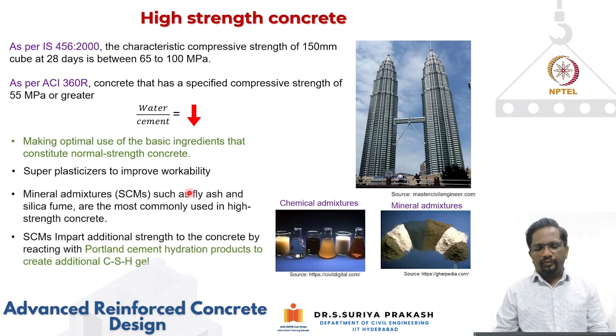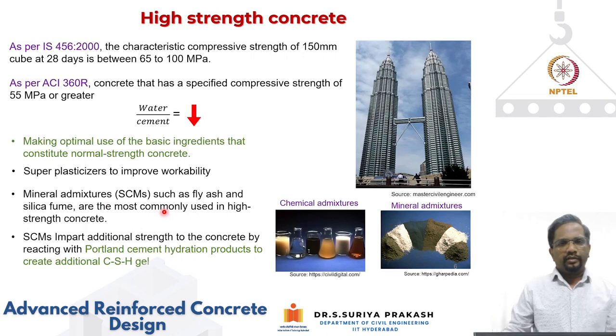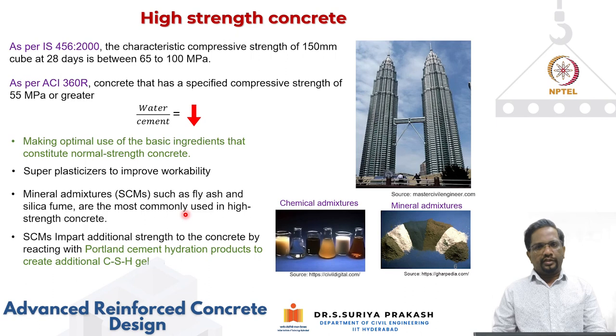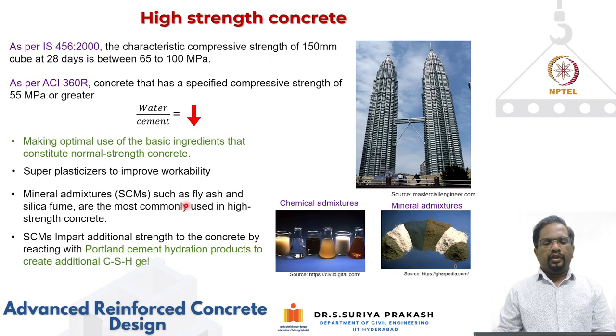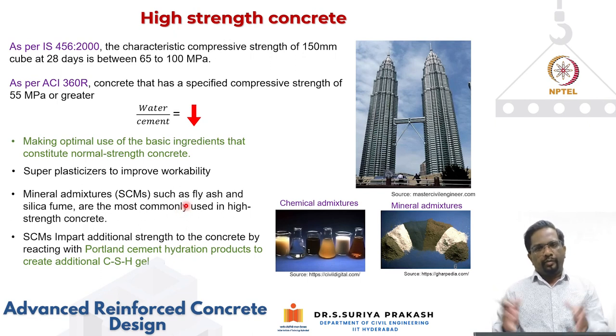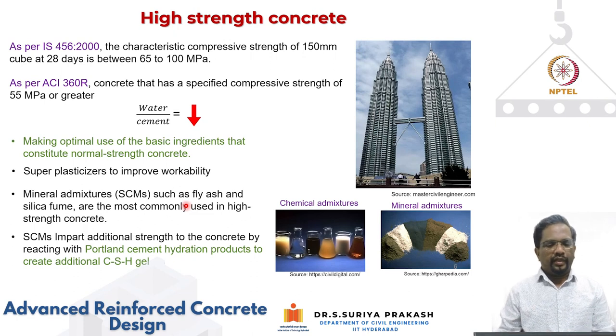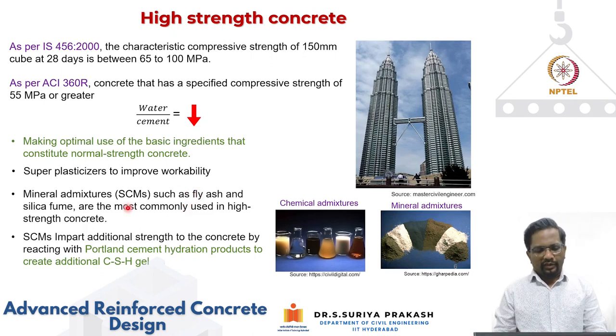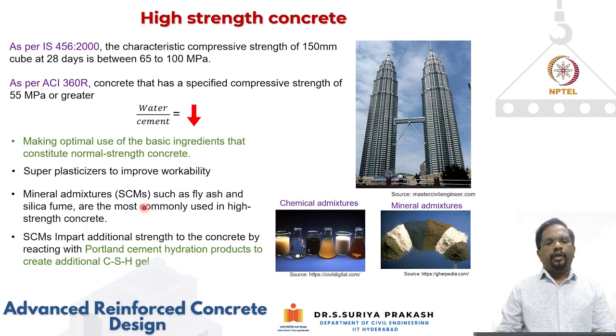Then another way is to add particles such as supplementary cementitious materials like fly ash and silica fume, which have various particle sizes, right? When you mix everything together with a proper particle packing approach, then for a particular volume, we can pack materials of different sizes, and you end up with a very dense microstructure. So that is another way of making concrete high strength.